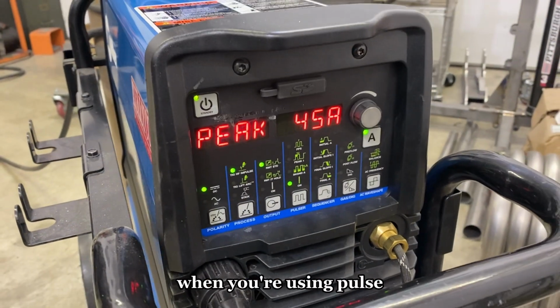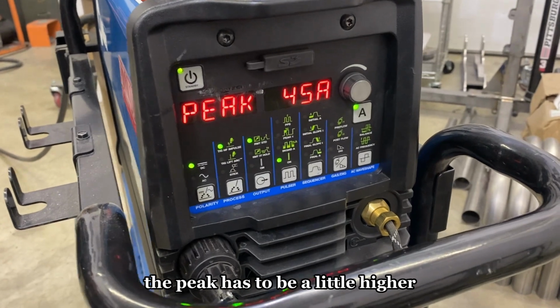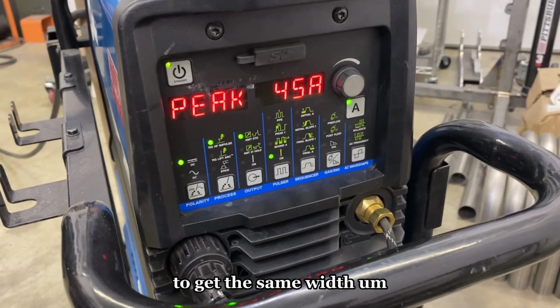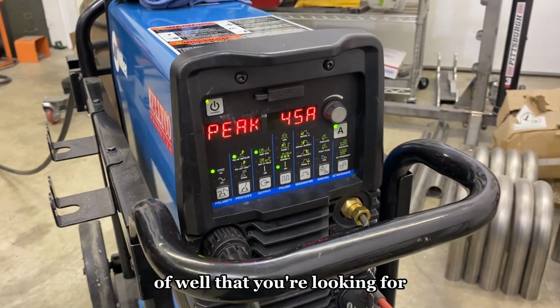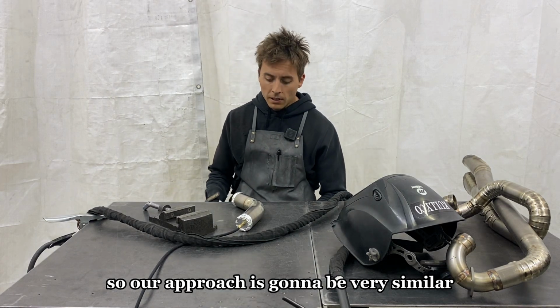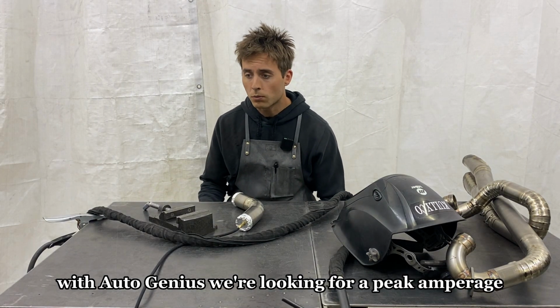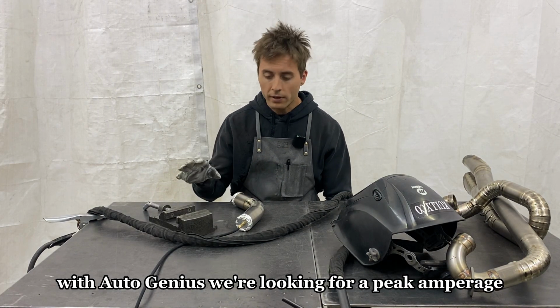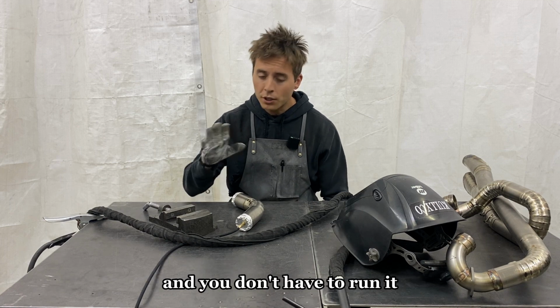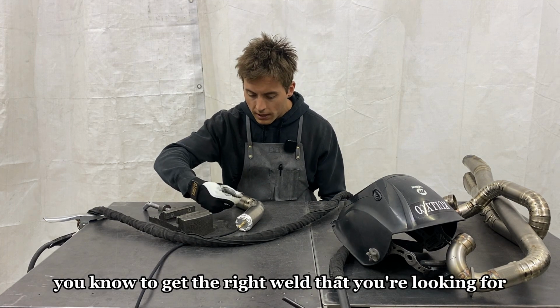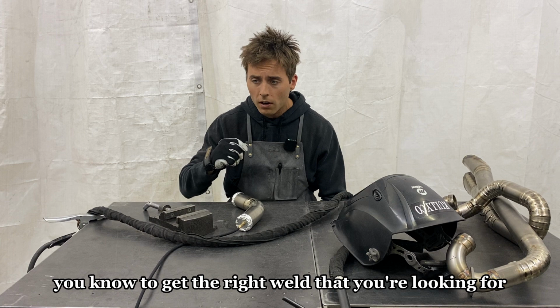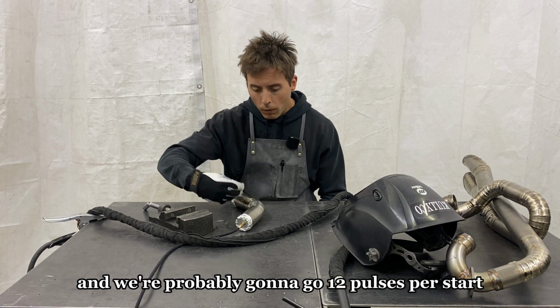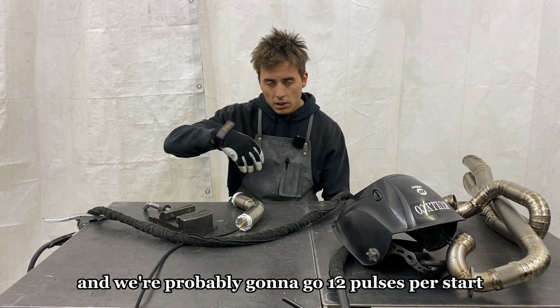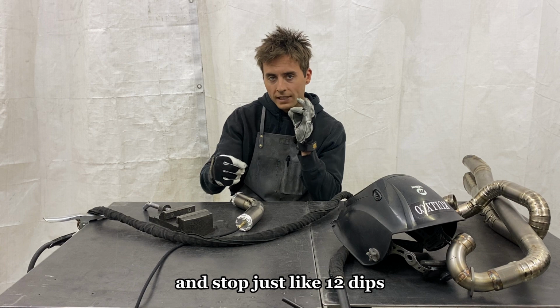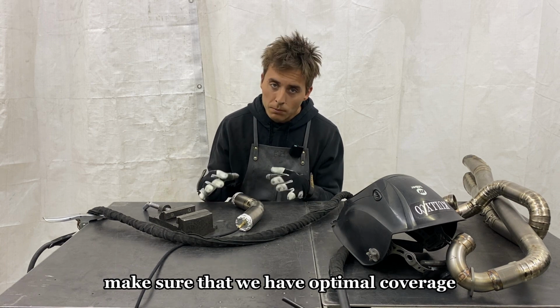When you're using pulse, the peak has to be a little higher to get the same width of weld that you're looking for. So our approach is going to be very similar with Autogenius. We're looking for a peak amperage where you can just slam the pedal and you don't have to run it to get the right weld that you're looking for. And we're probably going to go 12 pulses per start and stop, just like 12 dips, to make sure that we have optimal coverage.